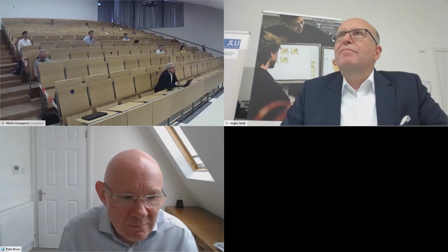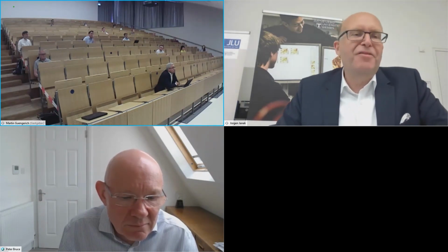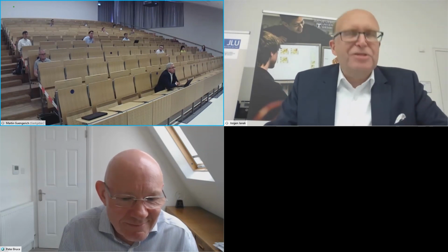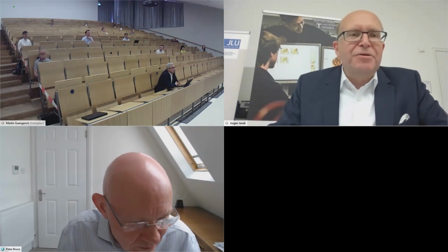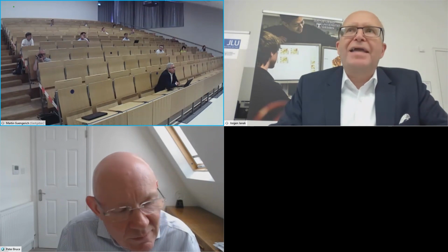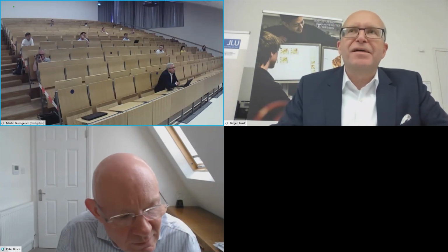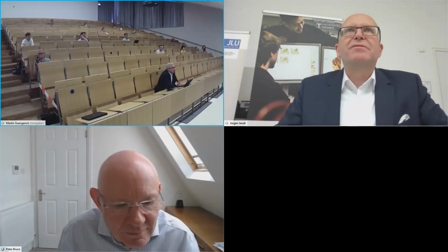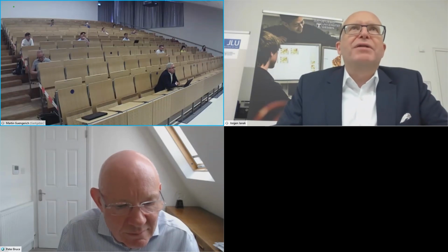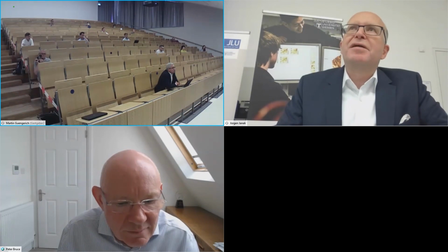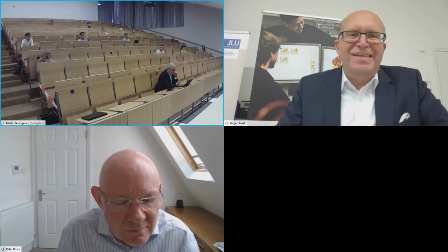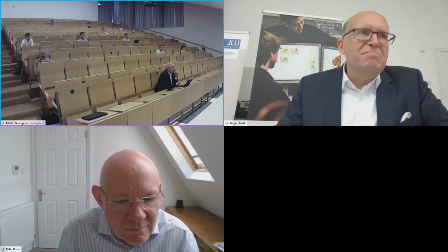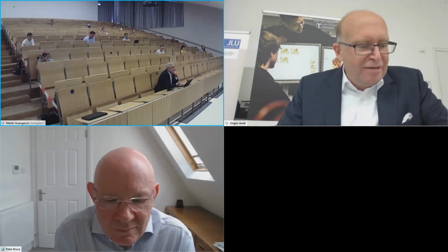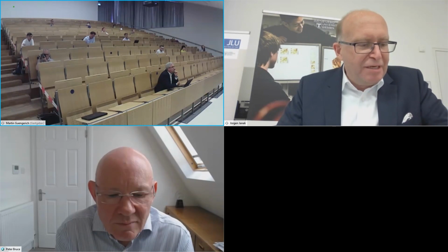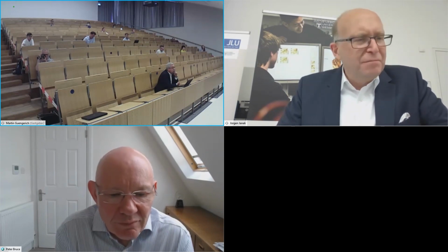Thank you. Okay, maybe a final question from an enthusiast in defect chemistry, Peter. If we form these oxygen species, it looked in your graphs as if one of the oxygen atoms is still more or less on a regular oxygen site, while another oxygen atom moved closer to that oxygen. So can that second oxygen atom, which comes closer to form something that can be considered an oxygen molecule, be represented as a kind of interstitial oxygen ion? I'm not sure whether one needs to describe that in terms of defect chemistry and Kröger-Vink notation, whether that makes sense. Is the second atom that moves to the other atom something like an interstitial oxygen ion?